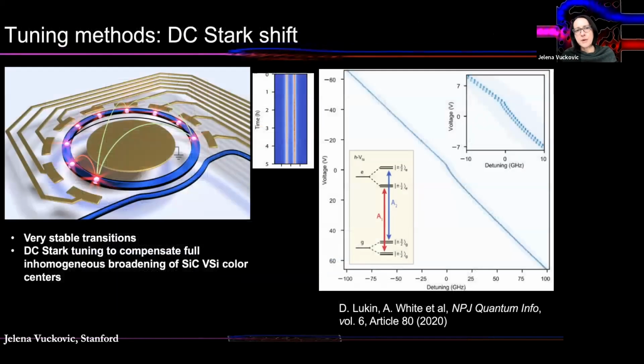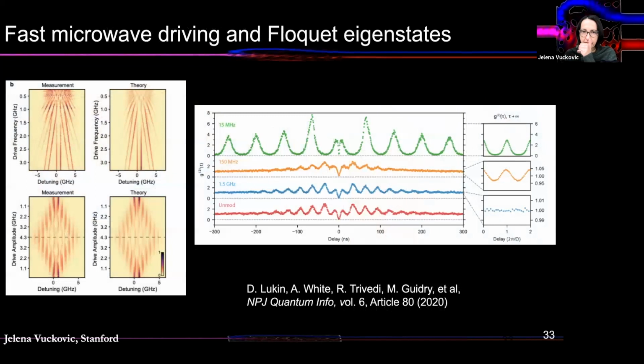And in silicon carbide, you can use DC Stark shift, just put electrodes and then tune your color centers onto each other. We've shown that we can tune them by 200 gigahertz by putting electrodes. And also in that process, we're not really affecting these transitions and stability. They're still very stable and preserve excellent properties.